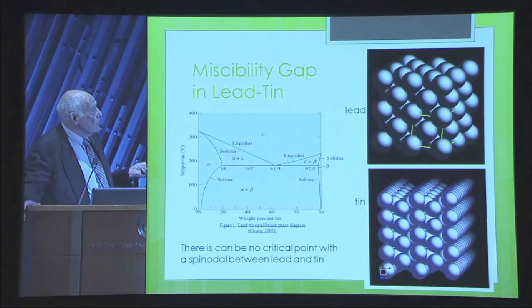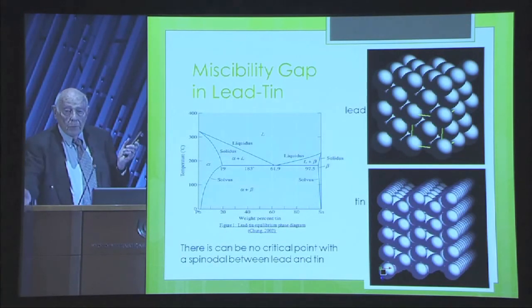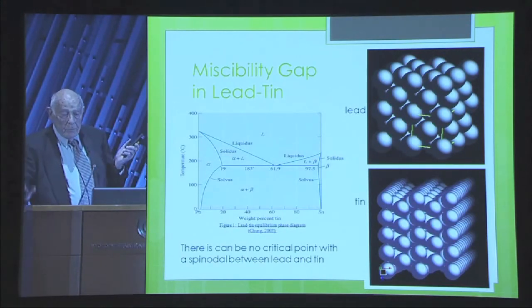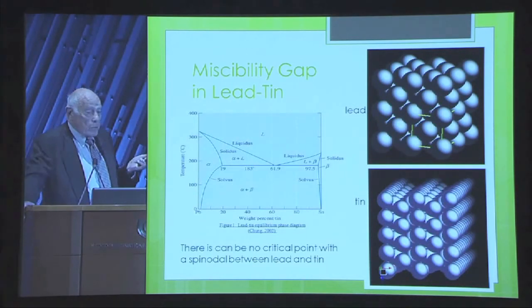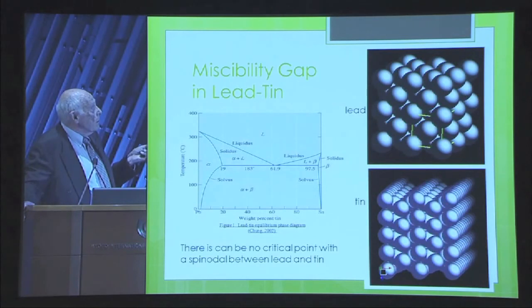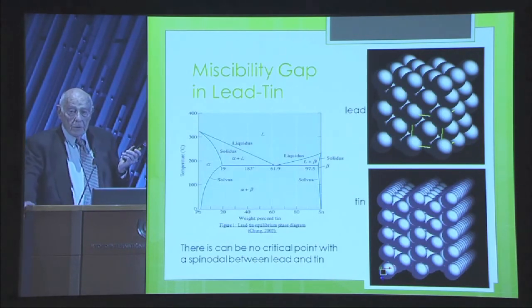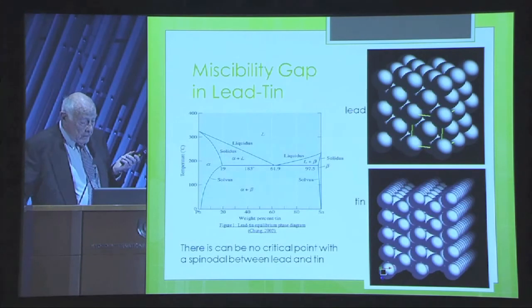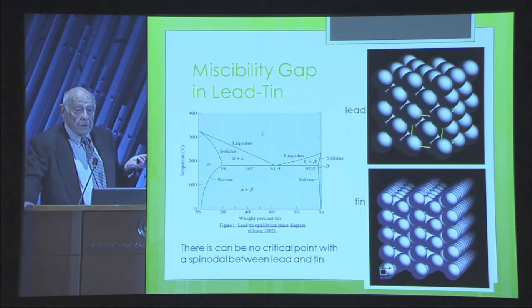There's this crystal structure of this composition. They would still be different because even though they would have the same composition, they would be so. Anyway, Turnbull had defended nucleation theory, and he had gone in and repeated the Swedes' experiment, and he showed that the way that tin precipitated was clearly by starting from nuclei and growing out. Well, I felt that that was not a fair test.